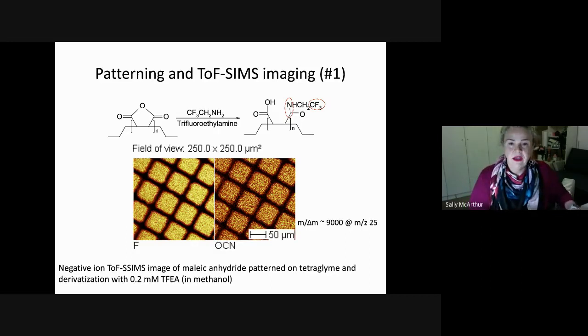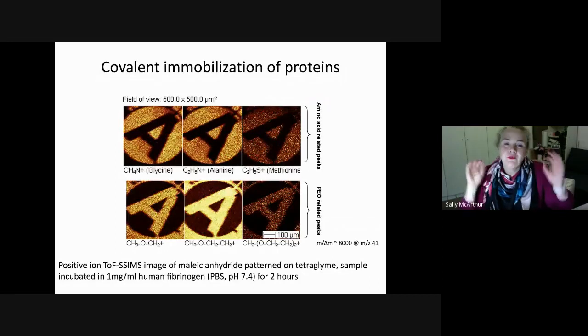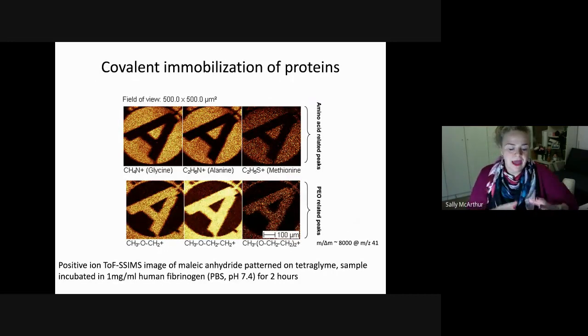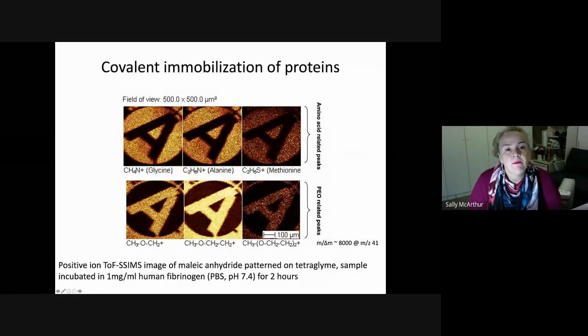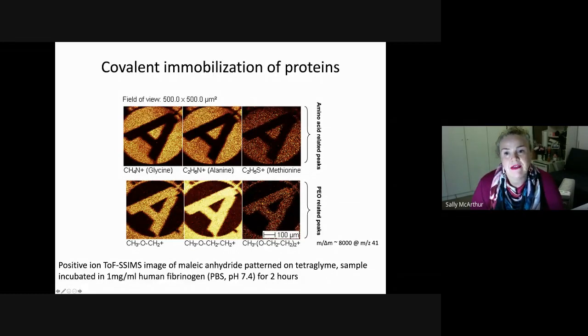And we did a lot of work in this area proving that these coatings are stable under these types of conditions. But the real test, obviously, is when you put it into use, and now you've made a maleic anhydride pattern on a tetraglyme background. The tetraglyme, nothing should stick to. No biomolecules should stick to it. The maleic anhydride should react with amine groups in a protein and allow us to actually immobilize proteins on our surface. So here's some TOF-SIMS imaging, where we're looking in the top frame at where the amino acid related peaks are. The bright areas are where the amino acid related peaks are found. So that indicates that there's protein attached to the surface.